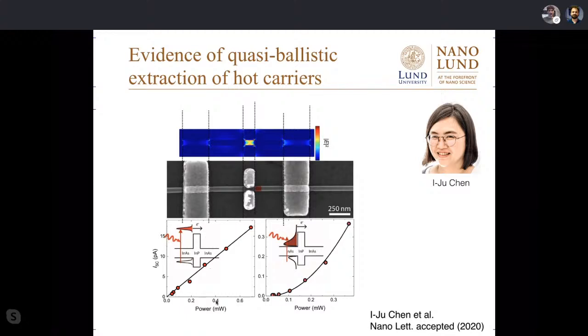And then she very nicely showed that as a function of power, she gets two distinct behaviors. In one case, she gets a linear behavior, meaning if you put more electrons up there, more of them fly over the barrier. So that's consistent with ballistic extraction. The other case is if you heat more, you get a bigger tail, but non-linearly so. So this is consistent with thermionic power generation, the way I described it before. So she showed really nicely that we can have control over this and can actually learn how to play with these different processes.